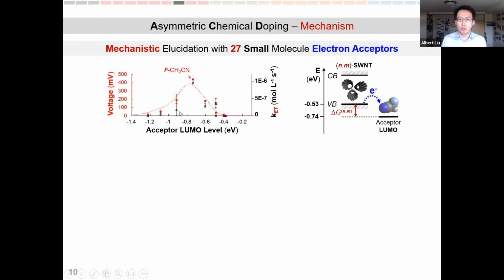To help you understand how to read this plot, the same data you saw from the previous slide actually collapsed into a volcano plot. So in this case, when we're stepping from right to left, we're gradually lowering the acceptor LUMO level, increasing the thermodynamic driving force of this electron transfer. And in doing so, we're increasing the rate at which we have voltage buildup. For the optimal solvent, we have fluorinated acetonitrile. But what is really interesting here is that once you get past fluorinated acetonitrile, further increase of this thermodynamic driving force actually leads to a decrease in the rate at which voltage is being built up.